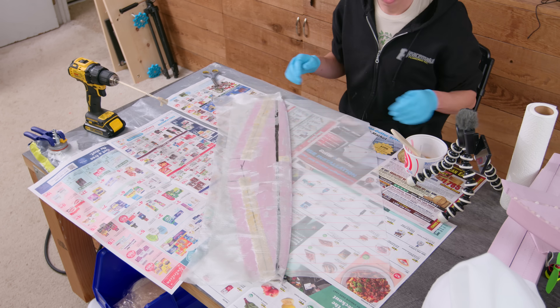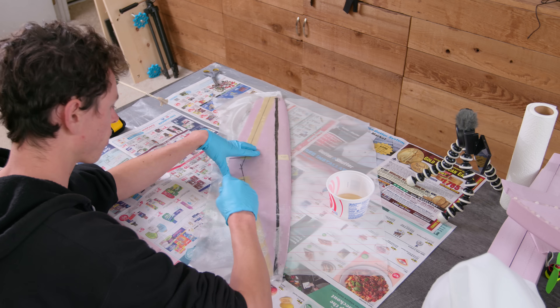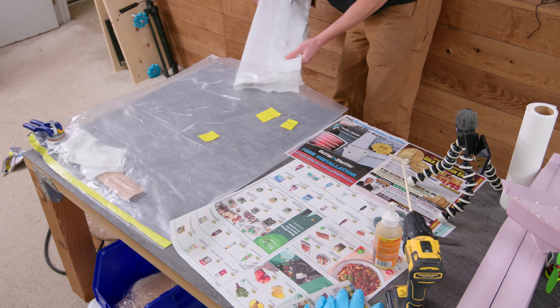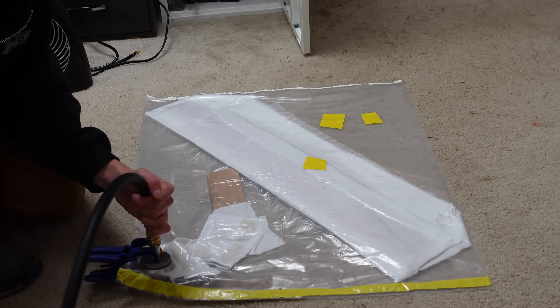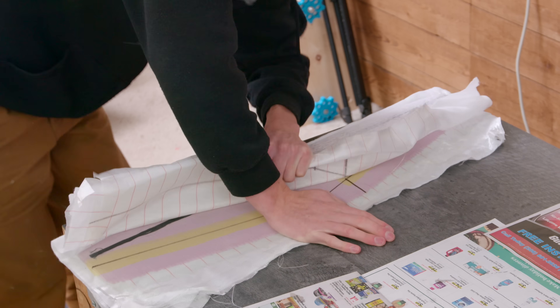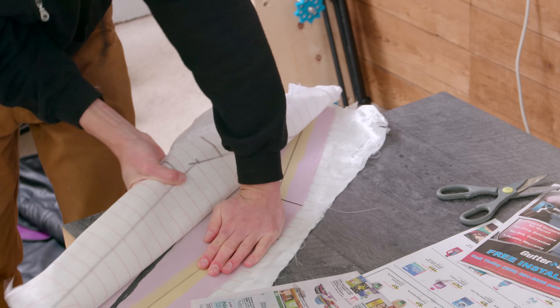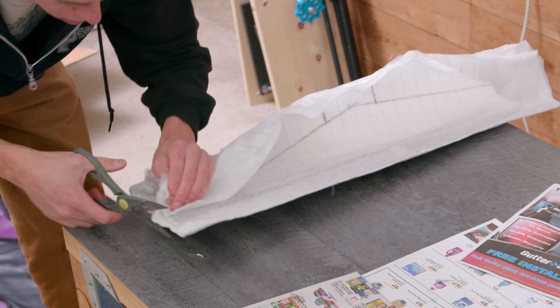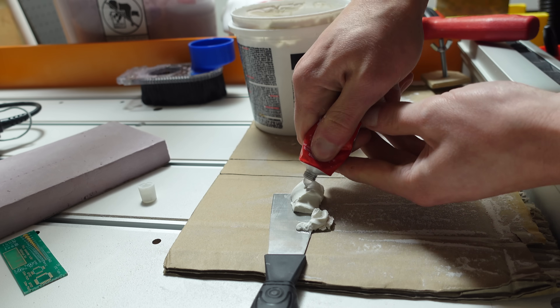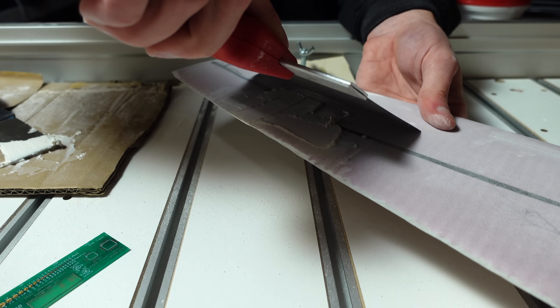I'm adding elevons to the horizontal stabilizer because it's easier than adding ailerons to these funky wings. Then came a layer of two-ounce glass and some peel ply over that. I stuck it into the vacuum bag and let the epoxy cure — or at least partially cure. I got a little too excited and started removing the peel ply before the epoxy had become fully rigid, which caused the foam and fiberglass to bend in a few spots. To try to reset the epoxy, I heated it up with a heat gun, but it also melted some of the foam underneath, so I had to do a little patchwork with some spackle mixed with goop glue so it wouldn't crack if it flexes.